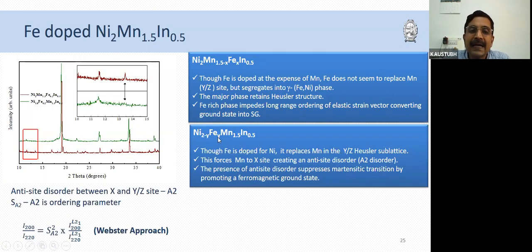Whereas in the case of nickel-iron alloys, though Fe should replace nickel, it replaces manganese at the Y or Z site of the Heusler lattice, and that forces manganese to come to the nickel site. So thereby it creates an A2 type disorder or an anti-site disorder. And if A2 type anti-site disorder is created, then it should affect the intensity of the 200 superlattice reflection. And it indeed does, as you can see. In the case of MnFe, there is this 111 and 200 peak, whereas in the case of NiFe, the 200 peak disappears, signifying that there is an anti-site disorder.